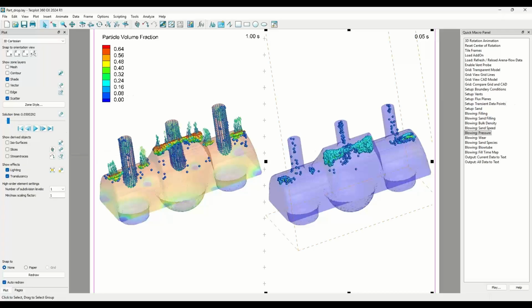Yeah, so in the first case, you left the pressure on. So at 1 second, it's not like we turned off the machine and watched the wind down, but rather stopped the blow at one second where the air is still flowing, and it's that aerodynamic drag that's holding the sand up to the vents. And in the second one, that's just the gravity falling, is that right? Yes, that is correct. Okay.